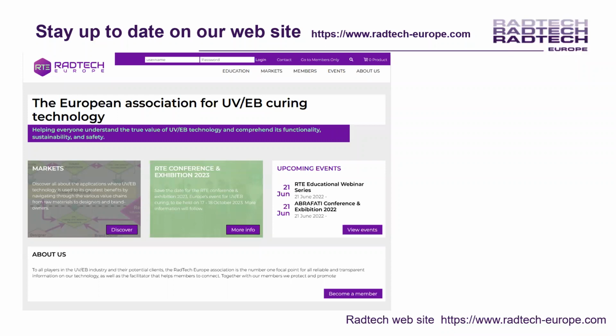And then there's another anonymous question. I am considering which wavelength is suitable for curing the interior layers of a UV resin system without cross-linking the outer layer. So if you want to keep a sticky surface, for example, I would say that UV LED technology would be easier, because you will be able to select one wavelength in order to cure in depth while reducing the maximum amount of impact on the surface. So in that case, you can use the advantages of the UV LED.